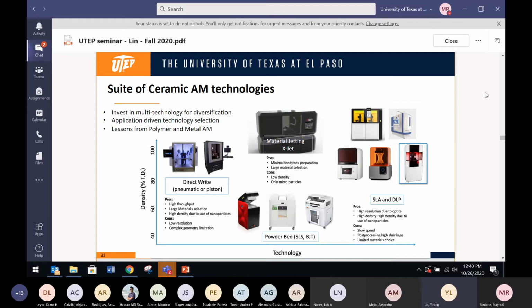And then the one in the middle is powder bed, using selective laser sintering or binder jetting printing. So you have a ceramic powder at the powder bed, and you shoot either using laser energy or using polymer binders to bind them together. And then you sinter them at the end, right? And then the one to the right is mostly the commercially available or successful printers, focused on photopolymers, using stereolithography and direct digital light projection, right? So this is basically mixing these polymers with ceramic nanoparticles, and then you can solidify the photopolymer. Later on, you do a sintering process to burn that out.